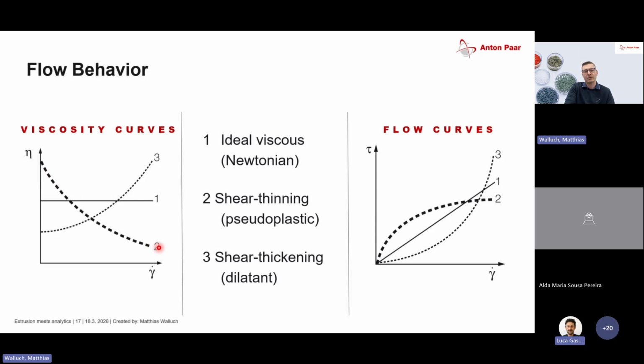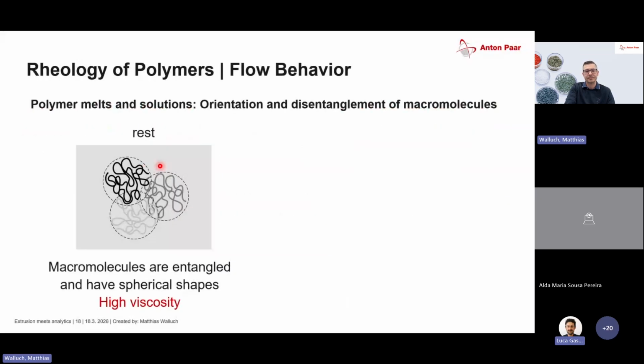And there are also shear thickening materials. This is, for example, starch measurement, also starch samples with high content of starch. So if you apply here a higher shear rate, you see that the viscosity goes up. But today we are going to talk about the second thing. So polymers are shear thinning materials.